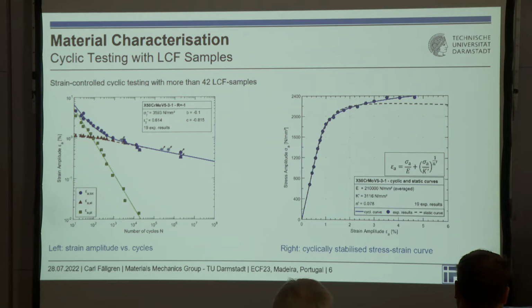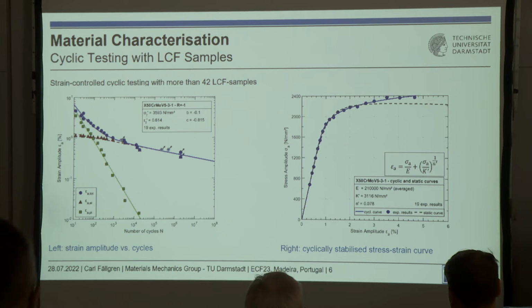We also did cyclic testing with LCF samples. It was fully reversed cyclic loading, and we made quite a lot of tests, and we also had some very high strain amplitudes of 4.75%. On the right side, you see the cyclic properties in comparison to the quasi-static testing properties for this chosen material.